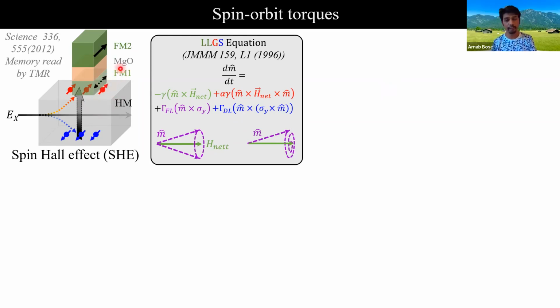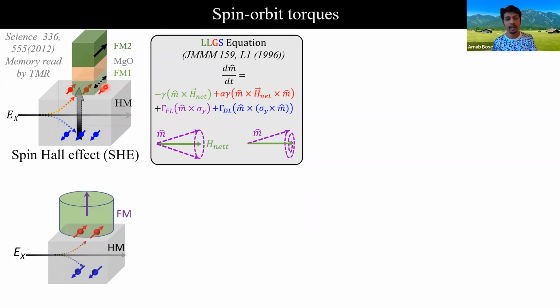And the state of the magnetization of the free magnet can be measured by reading TMR in the MTJ fabricated on this heavy metal. This has been reported in this pioneering work. Instead of having an in-plane magnet, we can also have an out-of-plane magnet on the heavy metal. This is particularly interesting for high-density memory applications. Here, we see that the accumulated spins from the spin Hall effect are perpendicular to the direction of the PMA magnet. So it cannot produce very efficient spin orbit torque for field-free or deterministic switching. However, we can do some tricks. For example, we can apply an in-plane external magnetic field that will tilt the PMA magnet a bit, and then spin orbit torque can be activated and it can switch. This has been reported in these pioneering works.